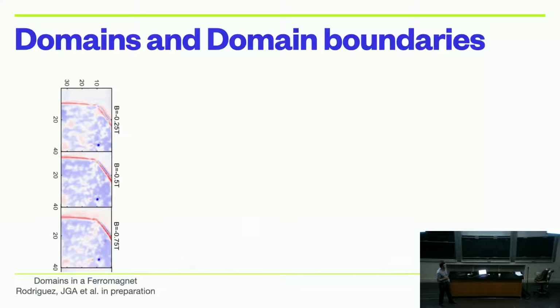Okay. Now I'm going to tell you about something else that happens around phase transitions, which is the existence of domains and domain boundaries. For those of you who remember, we talked about that energy landscape of ferromagnets. In that case, you could have two polarizations of the ferromagnet. Here I've got a spatial picture of a ferromagnet, where blue is spin up and red is spin down, and you can see how these domain boundaries form in a real material as you change the field or change the temperature.